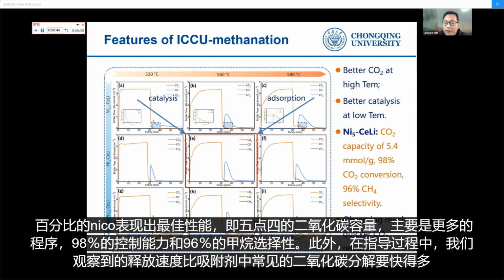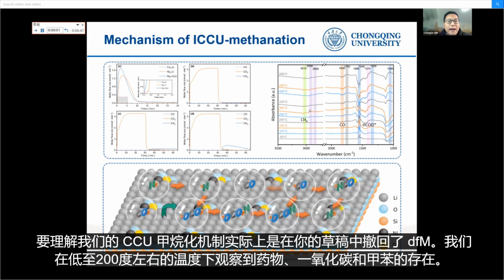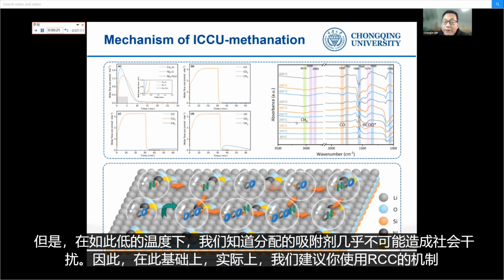Also, during the reactions, we observe a much quicker CO2 release than the common desorption of CO2 from the sorbent. To understand the mechanism of ICCU methanation, we tested the DFM by in situ DRIFTS. We observe the presence of methane, carbon monoxide, and formate at a temperature as low as around 200 degrees. However, at such a low temperature, it's impossible for CO2 desorption to occur from the lithium silicate-based sorbent.